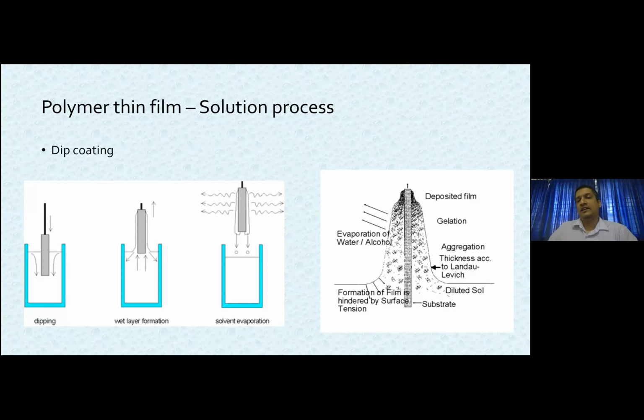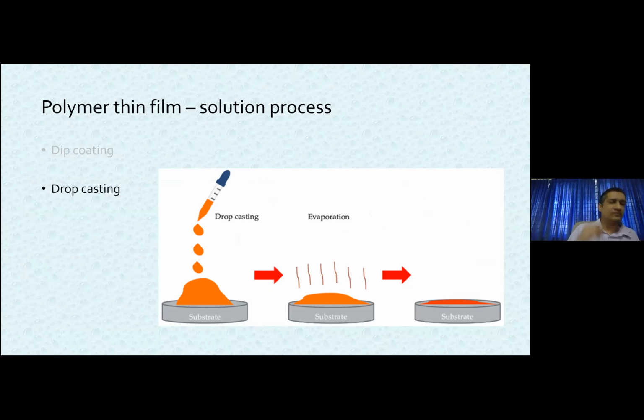During this process, various important parameters to be controlled are the rate of cooling, the concentration of the polymer in the solution, and the interaction between the solvent, the polymer, and the substrate. So over the period of years, we have expertise in doing this kind of uniform coating using dip coating technology.